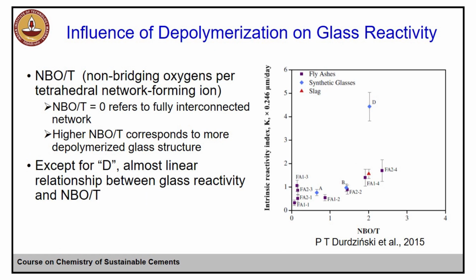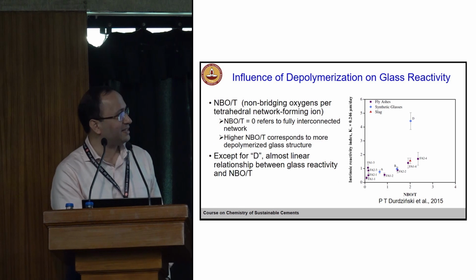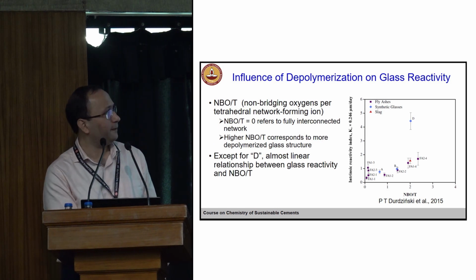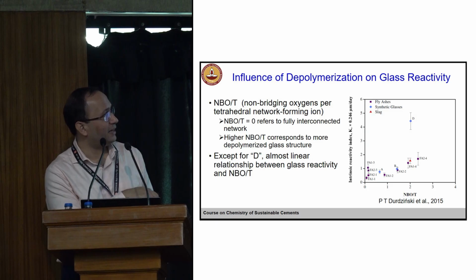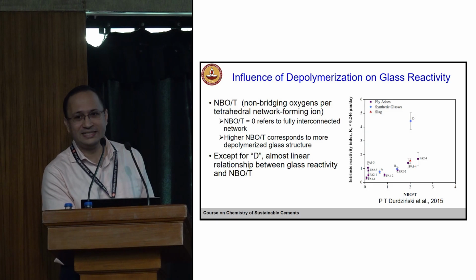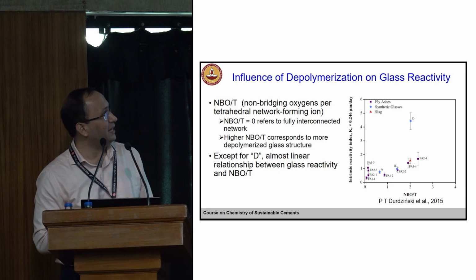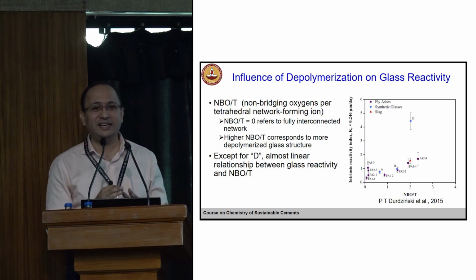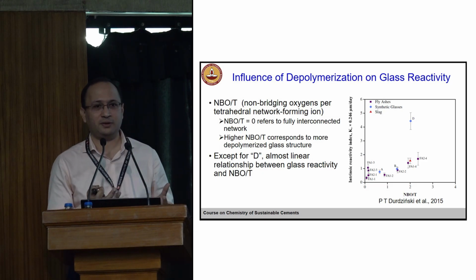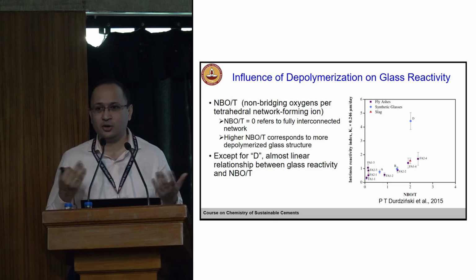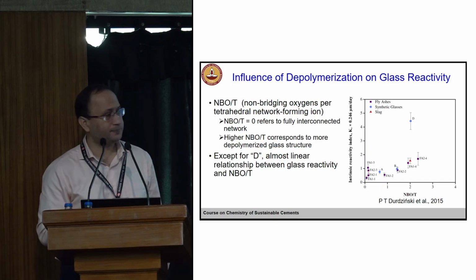That's what these guys did. You can see if you calculate this NBO/T, a higher number corresponds to more non-bridging oxygen. Basically, if the number increases, that means the glass is more depolymerized. And the reactivity also shows a direct trend: as NBO/T increases, your reactivity index also increases. That could be one way to look at different types of amorphous phases which may be present in your SCM.